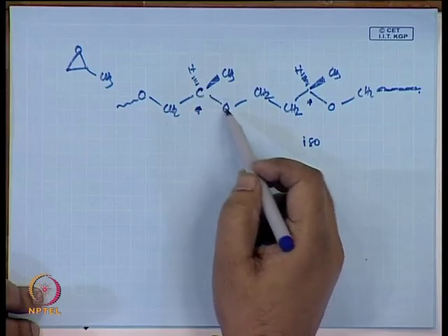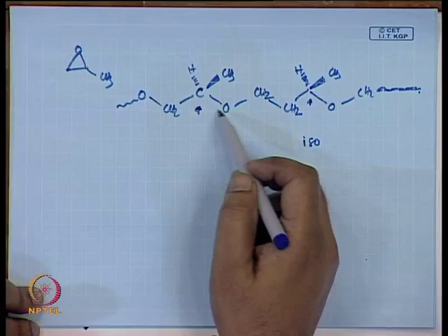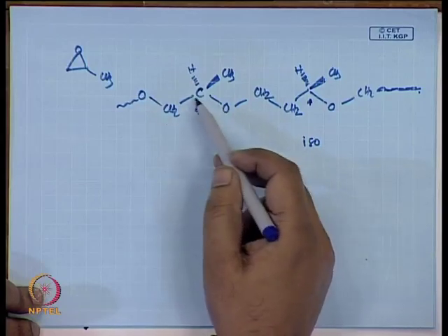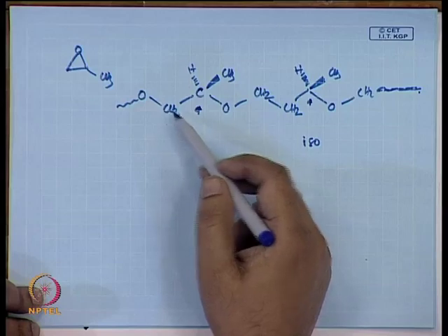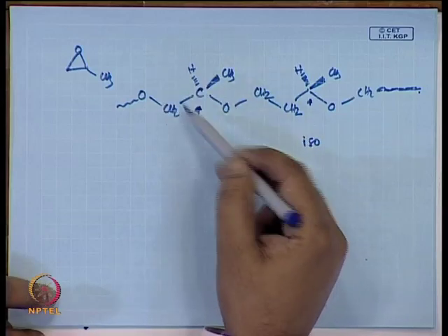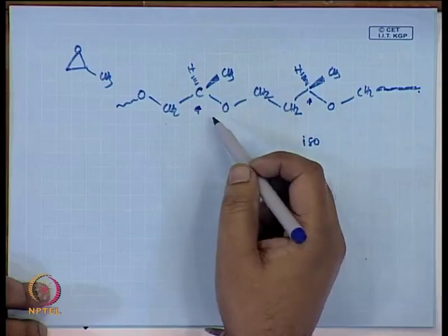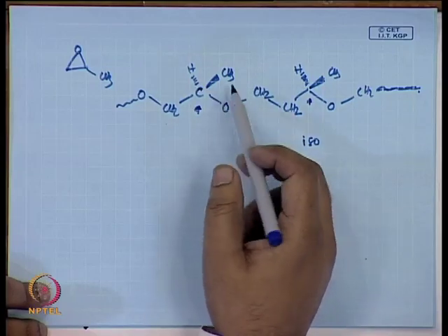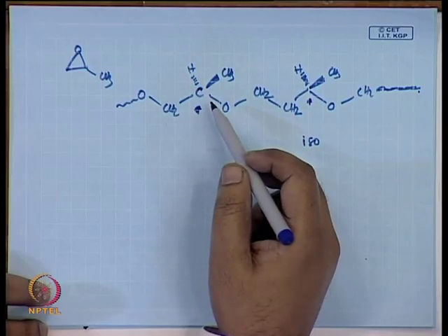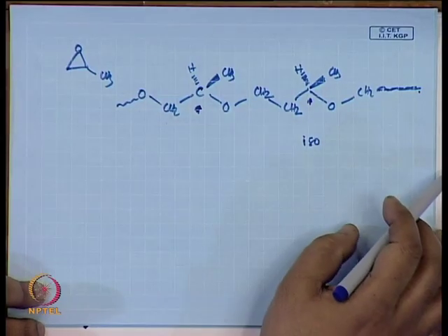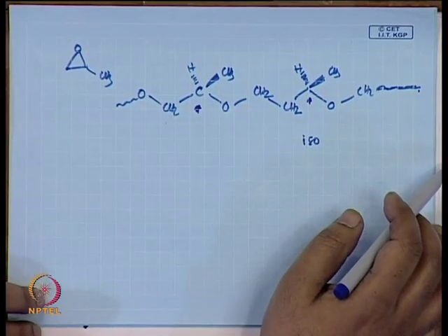Unlike chain polymers with only a carbon backbone, here you have oxygen as the next atom on one side, and a CH2 on the other. So, you expect that this will show optical activity, unlike a molecule like polypropylene, and indeed this type of polymer does show optical activity.